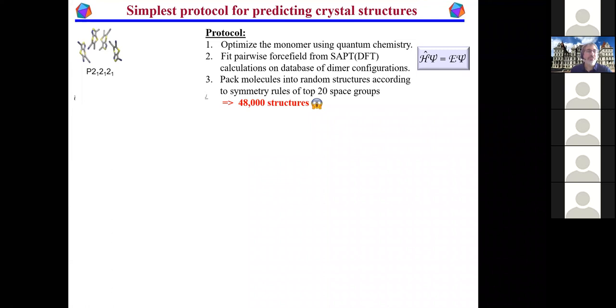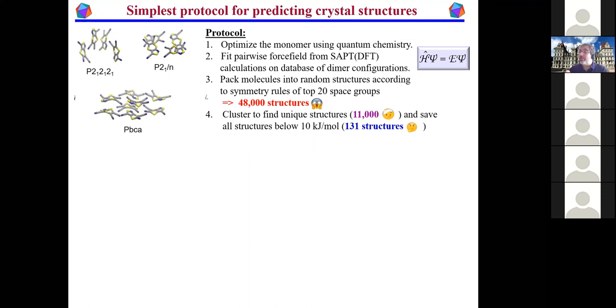And here are just some examples. These, of course, are minimized according to your force field, so you're getting to a local minimum, but you still have zillions of these things. Well, it turns out they're not all unique, so you can do some clustering in order to find out what the unique structures are. You still get thousands of them. We know that there aren't thousands of polymorphs in nature. But if you put an energy filter on there, say everything below, let's say 10 kilojoules per mole, we're going to keep. That gives you something more manageable, like 131 structures. And then you subject these to finite temperature, finite pressure, MD.